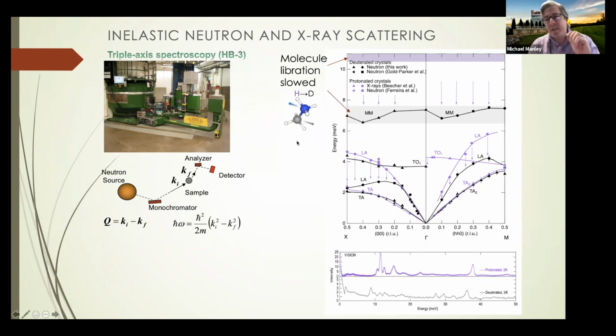But the interesting part, and the part that was a little bit surprising to us, was how strongly affected the longitudinal acoustic phonons were. So this is the longitudinal acoustic phonon. You notice it has a very steep dispersion. It's a compressional wave in the lattice, and it gets pushed down. So it's what we call mode repulsion. So the longitudinal acoustic phonon is slowed or repelled by the pushing of this libration mode down. That means that this libration is coupled to this phonon.